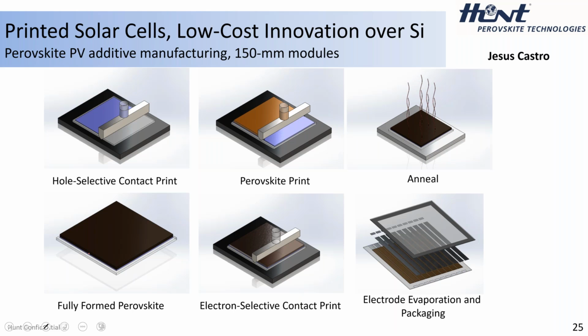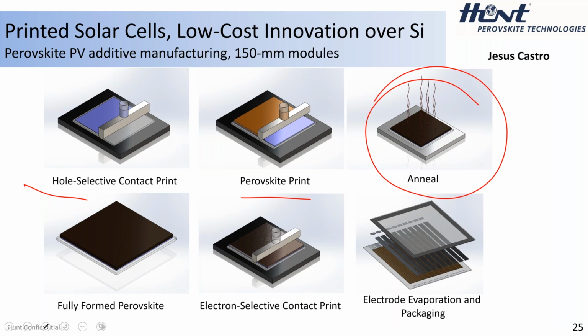Here's a little indicator here. So in a PIN architecture, we'll first coat the hole selective contact, coat the perovskite, and anneal to form the perovskite in situ. The orange here is to represent a precursor film that's formed on the surface and then requires annealing to have a fully formed perovskite. On top of that, we will coat the electron selective contact and finalize it with thermal evaporation of some back electrodes, or sputtering, what have you, but deposition of back electrodes, and then full encapsulation with back glass and an edge seal. And there's probably some laminate stuck in there too in this sandwich.